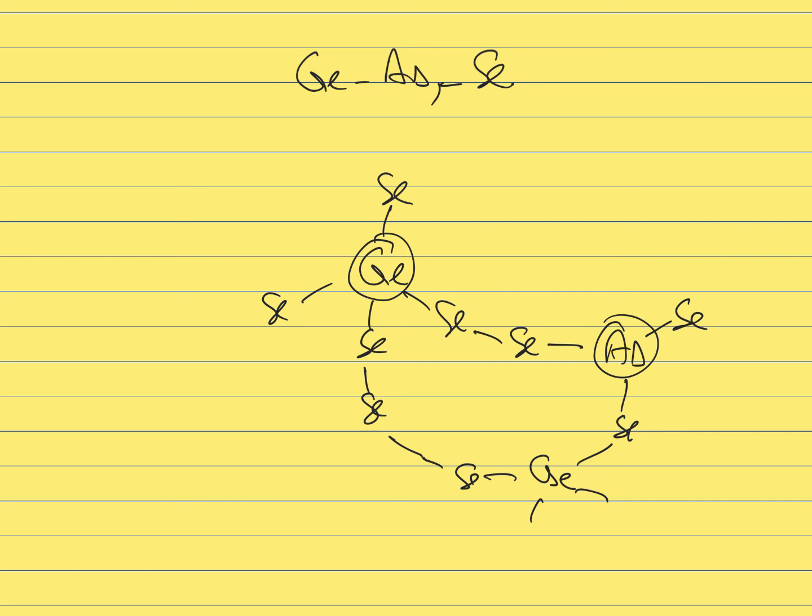And there can be some exceptions to that. You can sometimes have some homopolar germanium or some arsenic bonds. So there are always some types of defects that can be formed in those glasses, but usually the structure of chalcogenide glasses will be made of chains formed by the chalcogenide elements, some chains of selenium or some chains of tellurium or some chains of sulfur atoms. And this is typically what the structure will look like. You have those chains of chalcogenide elements that are cross-linked with each other by some atoms belonging to column 14 or column 15, some atoms like germanium, arsenic, etc.